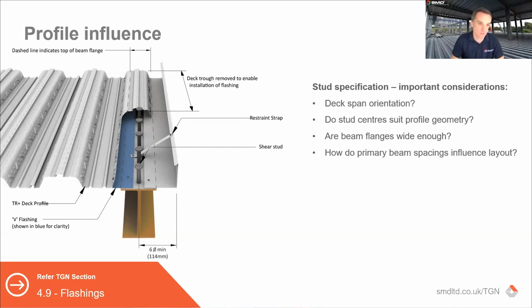Then we've got primary beams. Primary beams are less of an issue in terms of the longitudinal spacing. The challenge is more ensuring that you can get the studs onto the flange through a flat in the profile. So we do that by obviously firstly iterating and looking at the optimum setting out for the profile, and if we can, avoiding the need for flashings, but in many instances you can't avoid that. So we would then use flashings, which in this image is shown blue, where you would cut back the profile, flash to the beam, you can then get your studs on, and obviously the flexibility on a primary beam is a lot greater anyway, because you don't have the impact of ribs across the beam.